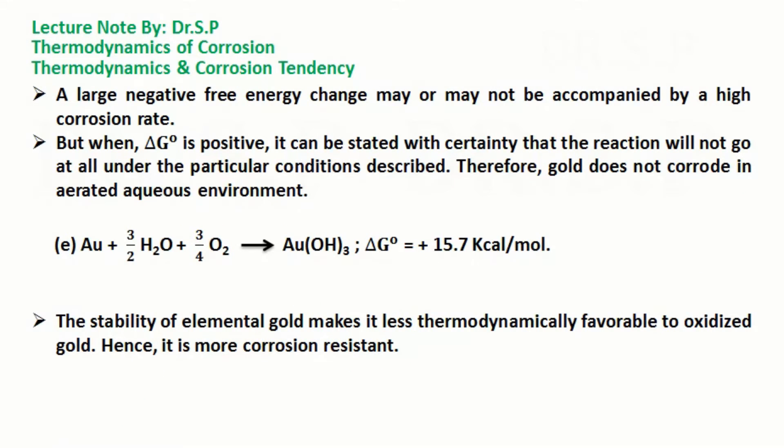A large negative free energy change may or may not be accompanied by a high corrosion rate. But when ΔG° is positive, it can be stated with certainty that the reaction will not go at all under the particular conditions described. Therefore, gold does not corrode in aerated aqueous environment. The stability of elemental gold makes it less thermodynamically favorable to oxidize.